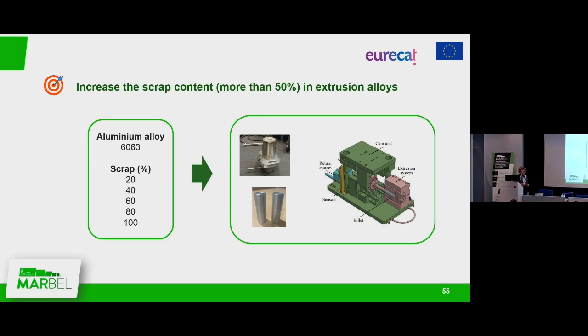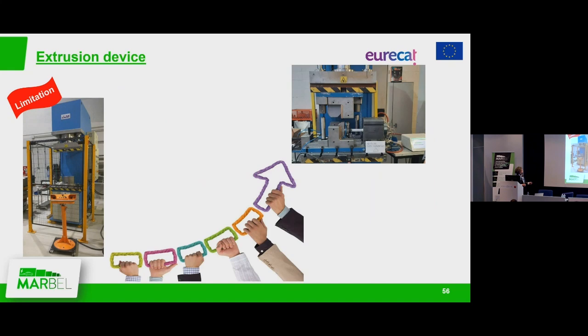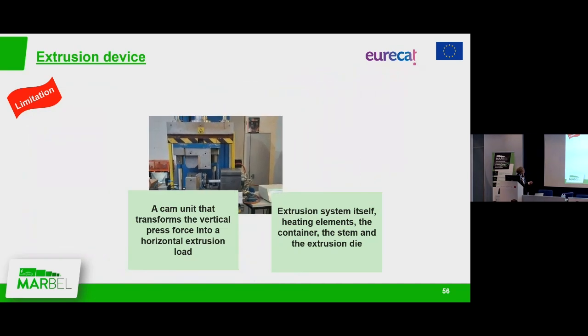I'm going to stop a little bit on this part because it was thanks to the MARBEL project that we have this tooling. In Eureka, we don't have the space for a full extrusion plant, but we have a very good team, and it was a very hard-working team because we have this load press, and our limitation was the force. In this case, we only have 100 tons. For this reason, we designed this special device, and it has two parts. One of them is this cam unit that transforms the vertical force into a horizontal extrusion load. And in this part, we have all the extrusion system with heated elements: container, stem, and the extrusion die.